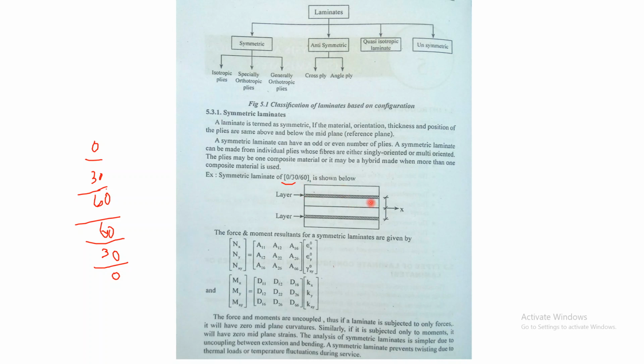What's going to happen in case of symmetric laminates? In symmetric laminates, if I consider the forces, the forces Nx, Ny, Nxy depend only on the normal strains. It doesn't have any implications from the moment strains.